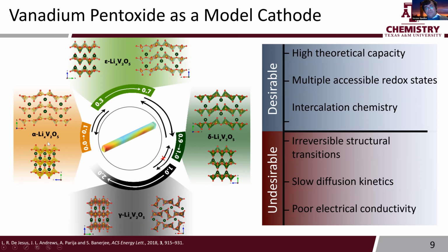and this shows the sequence of transformations that happen starting from V2O5 to this alpha slightly distorted structure into this more puckered framework, still layered, epsilon V2O5. And then you get some translations to happen. The layers slide along each other. You get this delta phase, and then ultimately going to a gamma phase. And then at still higher lithium concentrations, you stabilize this cubic omega structure. So some of these transformations, especially beyond gamma, are irreversible in the bulk, and this is a real challenge.